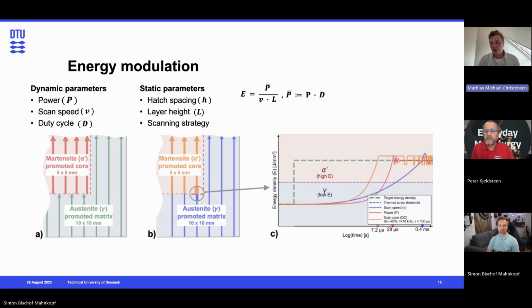Whereas if we're doing power, it's a little bit slower and might even overshoot a little bit as the power stabilizes due to control mechanisms. Whereas scan speed takes a long time, almost 0.4 milliseconds, which is a long time, and that's just due to the inertia of the mirrors that are positioning the laser, having a mass, right? And so they take time to stabilize and move. And so in doing so, we theorized that duty cycle would be the fastest parameter in order to get these sharp transitions between austenite and martensite.